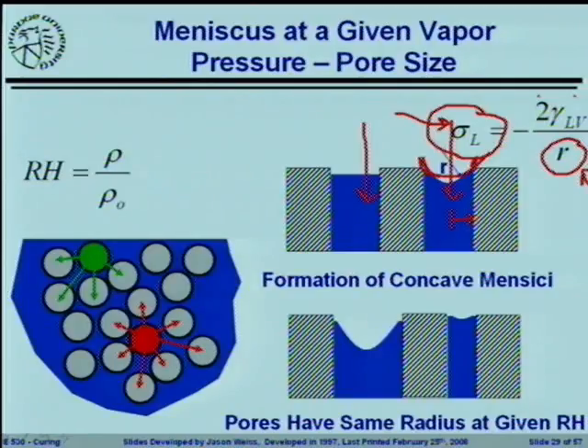So the smaller the cement, you're using silica fume, you're using really fine particles, that means you're going to have a smaller pore space in the system. Particles are going to be closer and closer together. That means that your capillary tension or your stress that's happening inside the system is going to be higher and higher. So that's one of the things that you can notice. Smaller pore spaces, higher strength concretes are going to get higher capillary stresses developing inside of them.